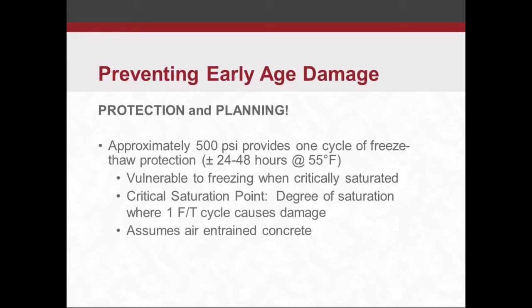So to prevent early age damage, again, planning. I can't stress that enough. ACI says about 500 PSI will provide one freeze-thaw cycle protection, and you get about 500 PSI within about a day or two at curing temperatures of about 55 degrees. That's another temperature that you'll see somewhat consistent throughout some of this presentation, 55 degrees. But that 500 PSI, that's just one freeze-thaw cycle. Multiple freeze-thaw cycles, at that strength, it's probably not going to hold up.